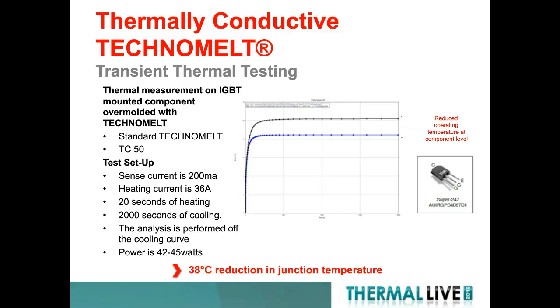Again, we're comparing the standard material that's unfilled with a thermal conductivity of 0.2 watt per meter-K, and the thermally conductive material, TC50, with a thermal conductivity greater than a half watt per meter-K. And the image on the right is the output off the cooling curve, and you see the difference in those two curves equating to about 38 degrees C of the junction temperature measured. So the thermally conductive material allows for the heat to dissipate through the encapsulating layer, allowing that junction temperature to remain significantly cooler.